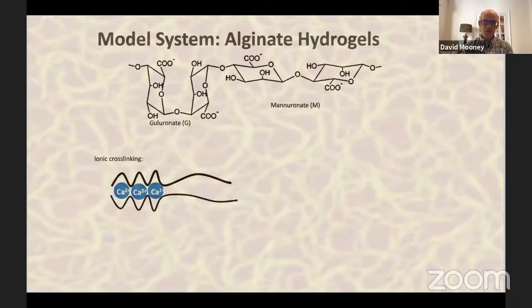So to explore this, we've been using a particular model system that I'll describe a little bit here. It is a polysaccharide called alginate that is a block copolymer comprised of two types of sugars, what I'll abbreviate as G sugars or M sugars, and these are organized into blocks. The relevance of this block structure is that only the G blocks can actually participate in cross-linking or formation of a hydrogel from these polymers. And when these polymer chains cooperatively share divalent cations, such as calcium, between the G blocks of adjacent polymer chains, this induces gelation. The M blocks don't participate in this process.